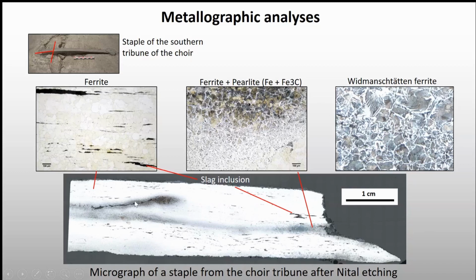And this band structure here is just normal, because if you have a heterogeneous material and you forge it to a long bar, the heterogeneities will have a tendency to form this kind of bands in the structure. So it's not intentional, it's due to the forging. We can see that we have structures of Widmanstätten ferrite here, which are typical of rapid air cooling, which was typical for medieval blacksmithing. So here we have very typical iron, which can be compared to what we have seen in other monuments before. All the small black dots here are the so-called slag inclusions.